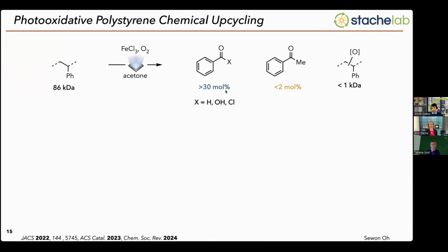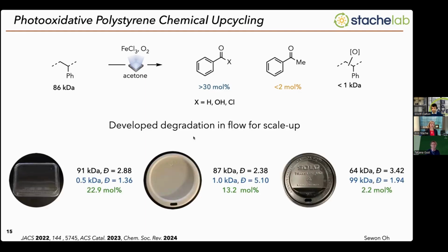So about 30% of the polymer was converted into primarily benzoic acid. Small amount of benzaldehyde and benzoyl chloride, but these are very quickly converted into benzoic acid. A very small percentage of acetophenone, and the mass balance was just being oxidized styrene oligomers. He was able to further show that you could improve this process to get approximately 50 mol% of the polymer into benzoic acid. We also developed a degradation process in flow, so we could try and scale this up to multi-gram scale in a shortened time frame with the same sort of product selectivities.